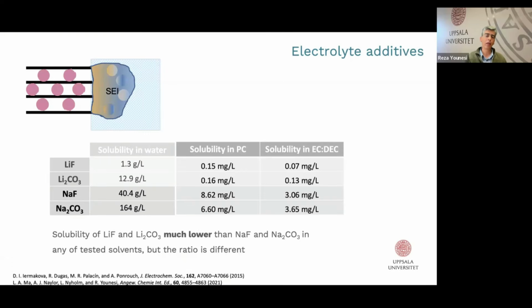So we use these species as electrolyte additives. Basically, we added those species in advance to the electrolyte solution. For example, we added lithium fluoride to the solution to see if that influenced the composition of SEI and its aging. Just to highlight again, this is a very model system - we know in reality SEI is way more complicated than this. There are organic species in SEI which are very difficult to synthesize in advance and add beforehand to the electrolyte solution, but we try to use a model system to mimic the situation.